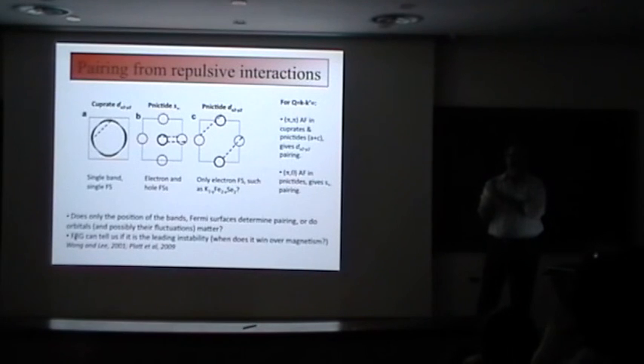I've not heard anything. And the photoemission? Nothing. Maybe I think this is very dependent on the system, because in potassium-doped samples there is no anisotropy of resistivity above the structural transition. It's very peculiar to cobalt-doped samples in barium.